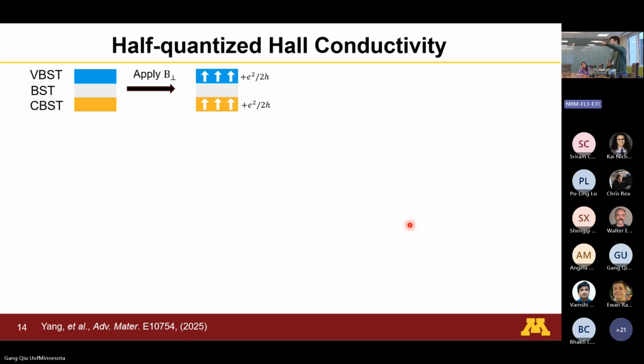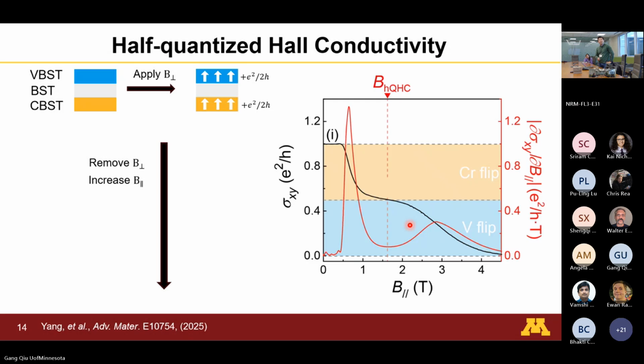And we start to apply an in-plane magnetic field, right? So you can sort of imagine what will happen, right? The softer layer will rotate first, and then the harder layer will just follow, right? So that's exactly what we did, right? We remove the perpendicular field and increase the in-plane field in this case.